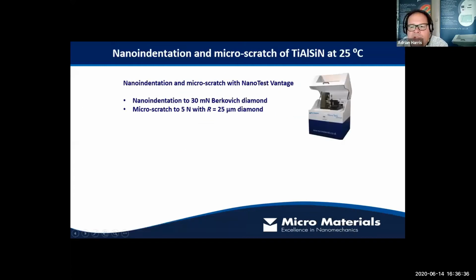So, nano indentation of these 2 coatings at room temperature. We used a NanoTest Vantage for this. We're using 30 millinewtons load and a Berkovich indenter tip. And we did some scratch testing as well, also with NanoTest Vantage, but actually with the high load head. So the nano indentation is performed with our low load head, and the micro scratch is performed with the high load head. We did some scratch testing for 5 newtons with a 25 micron radius diamond probe.